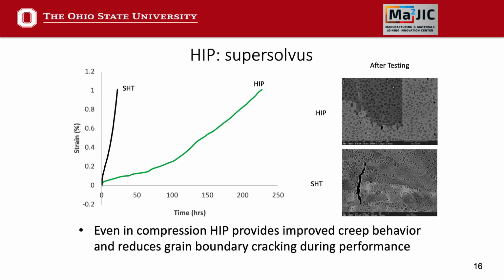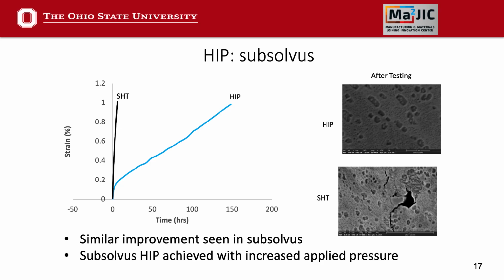Yes, we've seen some very interesting mechanical behavior, particularly when looking at creep, which is the critical application for a lot of these higher gamma prime alloys. We found that using the supersolvus heat-treated condition, we can create microstructures that have behavior that is superior to even that of the wrought condition. We also found that using HIP, we can push that behavior window even further. Compared to the traditional solutionizing heat treatment, we have much better behavior both in the subsolvus and in the supersolvus when using HIP.